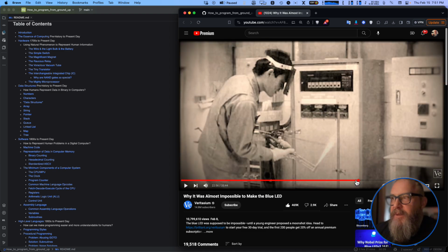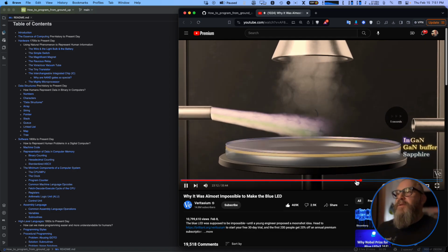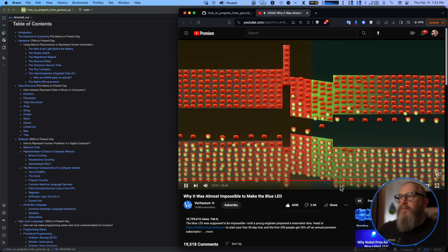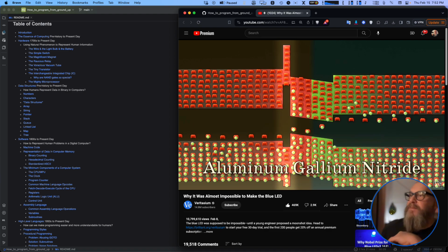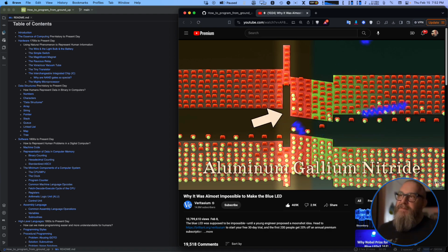All right, right here. This allowed him to use some, just talking about electrons leaking back into the gallium nitride layers. Unfazed, within a few months, Nakamura had fixed this too, by creating the opposite of a well, a hill. He returned to his reactor one more time to make aluminum gallium nitride, a compound with a larger band gap that could block electrons from escaping the well once inside. So he's working through all these chemical layer processes, just experimenting with all kinds of stuff he can get his hands on before he runs out of money. And his boss is super pissed. It's great to watch this video about how this all happened because it's a very common story and kind of sad.